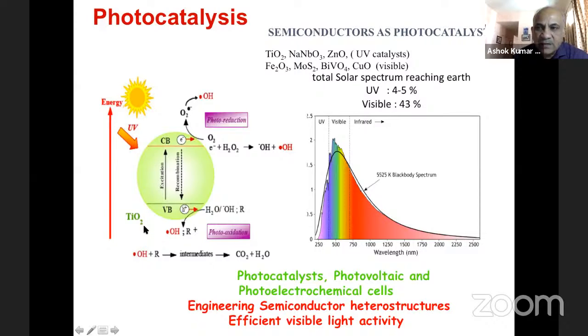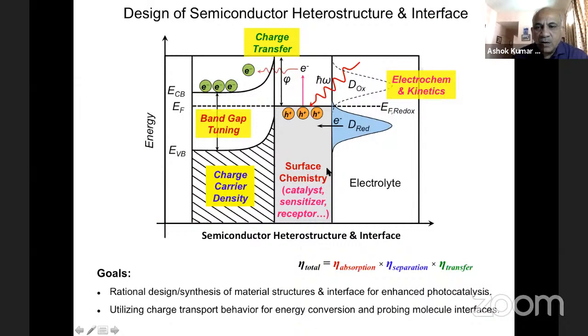And TiO2 as such is a very common material, but it is a UV catalyst because it has a band gap which is around 3.3 electron volts, which falls in the ultraviolet, whereas you would like some things to be in the visible range, say 2.5 electron volts and something like that, so that you can capture maximum number of photons. So a lot of our work is on design of these materials, which will have effective band gap lie in the visible. So what you want is you want to look at improvement of the efficiency.